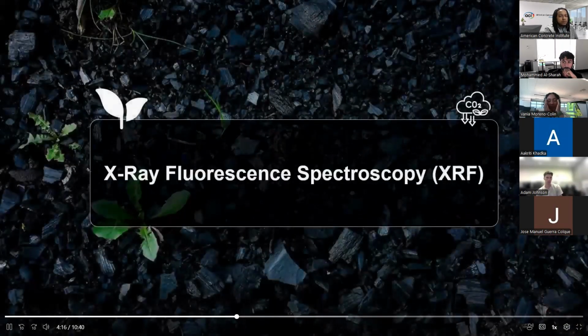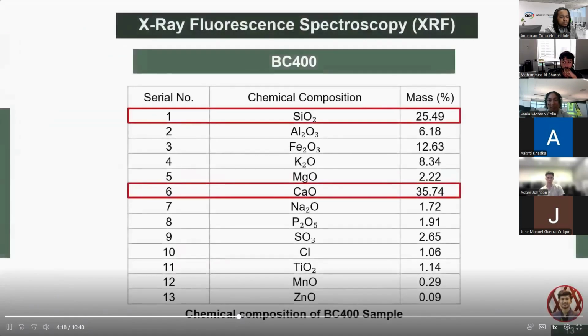In the XRF test results, we found 25% of silicon dioxide and 35% of calcium oxide. This value helped in the strength gain of mortar, which we will see in the upcoming slide.